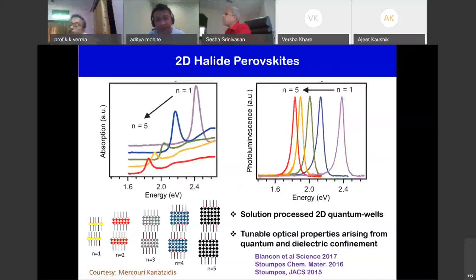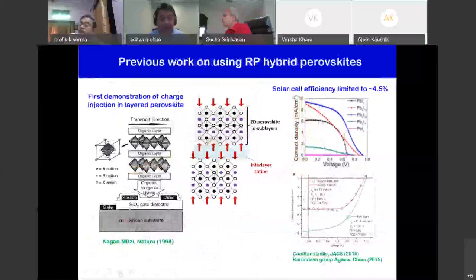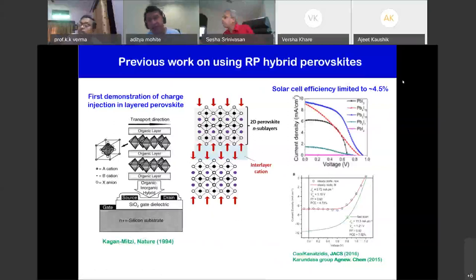And so we took these materials because they were way more stable than this three-dimensional structure. And we made photovoltaic devices. Now, of course, previously people had made these devices. In fact, the first evidence of putting any kind of current into this device was done in the 90s by David Mitzi and co-workers, where they showed that you can make good FETs out of this. Of course, people had more recently tried to make photovoltaic devices, but these efficiencies were quite low, about 4%. And so we wanted to see what was the issue with this.